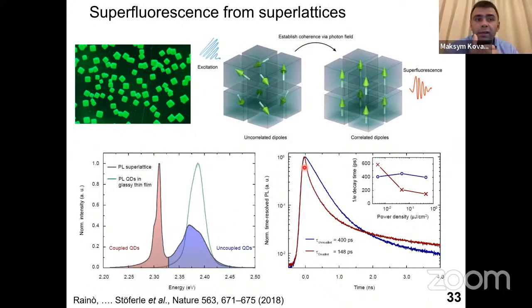And then as you start increasing the power density for your excitation, you start seeing the shortening of the radiative rate without losing the quantum efficiency, which means that you have pure acceleration of emission. So what happens is that your initially incoherently excited quantum dots build coherence across themselves if they are in sufficiently close proximity. And for this effect, they have to be within half a wavelength from each other. So if in that volume you have a sufficient number of photoexcited quantum dots, they start building coherence across themselves and establish large multi-particle dipoles, which emit coherently, and emit light with a faster radiative rate because they have a higher oscillator strength.